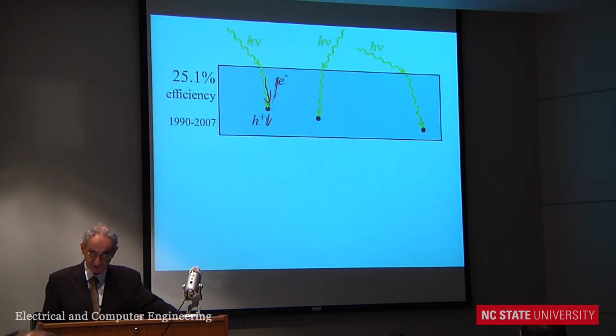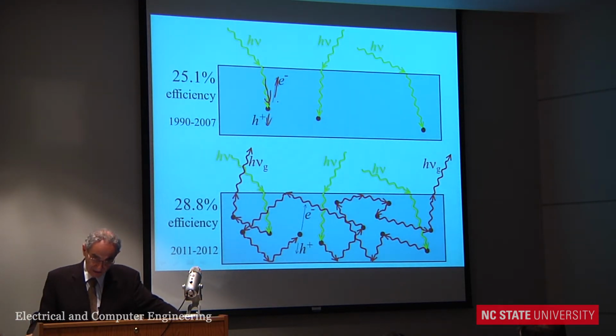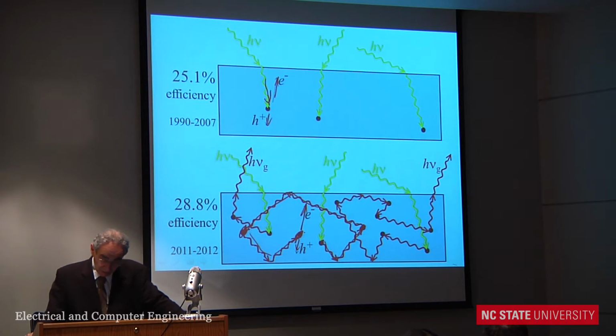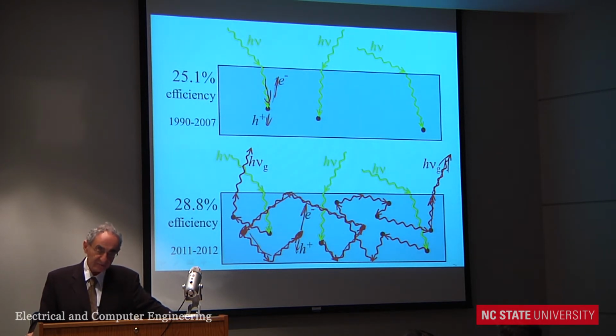However, to have high efficiency, the picture has to change. Let me show you the picture today. The picture is the sunlight comes in, it produces an electron hole pair, that instantly recombines back into a photon. The photon bounces around, gets reabsorbed, produces another electron hole pair, which recombines, produces a photon again. Absorbed, re-emits. Absorbed, re-emits, finally does not re-emit, instead gets collected, okay? Or, of equal importance, sometimes the photon just escapes. And you might think that's bad, but it's actually good for occasionally a photon to escape from the front surface. Okay, so this is a very different picture than what you have in textbooks.